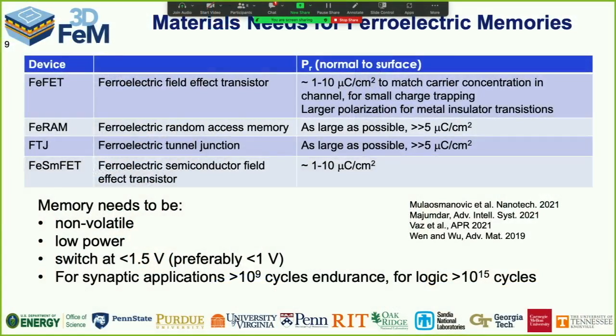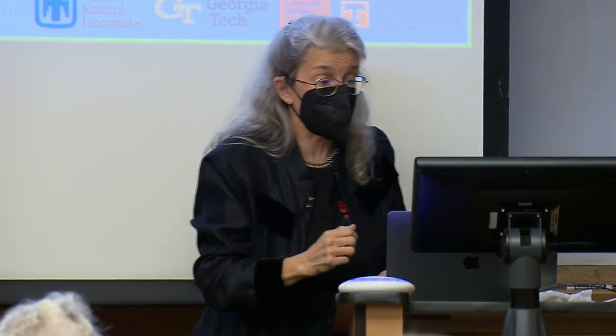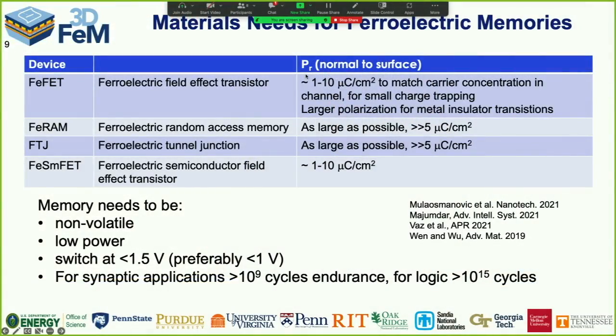So what do I need out of this ferroelectric? What I need out of this ferroelectric is going to depend on what device instantiation I use. So if we are going to use a ferroelectric field effect transistor, where we're using the spontaneous polarization to control the carrier concentration on a semiconducting channel, if I have a polarization up, it's positive at that surface. So I can, for example, drain carriers out of some channels. If I flip it the other direction, the carriers will accumulate in different ways. That's how a ferroelectric field effect transistor works. And for that application, for realistic semiconductor carrier concentrations, I need about 1 to 10 microcoulombs per centimeter square. Anything beyond that doesn't help me at all.